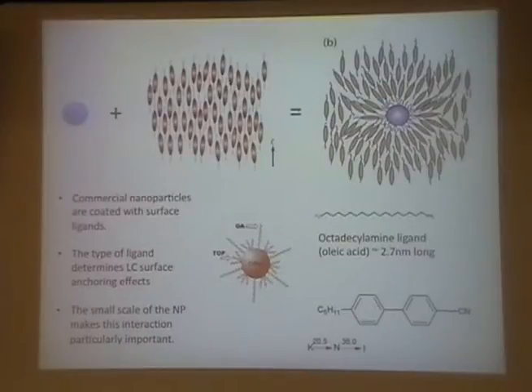Okay. With the bare particle, then you have the metal or semiconductor surface. It's going to have some different property. There's always going to be some surface property that you have to take into consideration. So you just have to know what's on there. Yeah, because if there is no surface treatment, in most cases it would have the tangential anchoring, and we can simply get this kind of homeotropic anchoring by treating with the surfactant. This is just like the surfactant, right? It's the same kind of thing. Yeah. The same molecule, really. So no need to treat the particle. Mm-hmm.